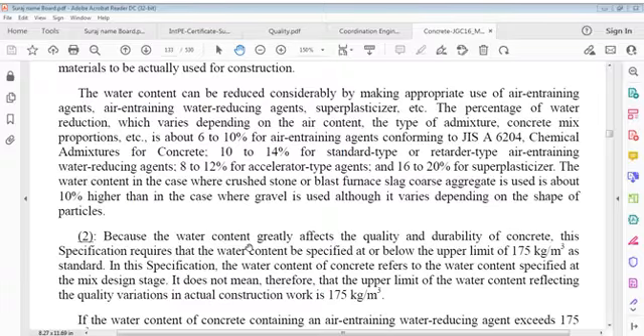That's 6 to 10% for air entraining agents, and chemical admixture 10 to 14%. Standard type or retarder type air entraining water reducing agent is 10 to 14%, and 8 to 12% for accelerator type agents, and 16 to 20% for superplasticizer.